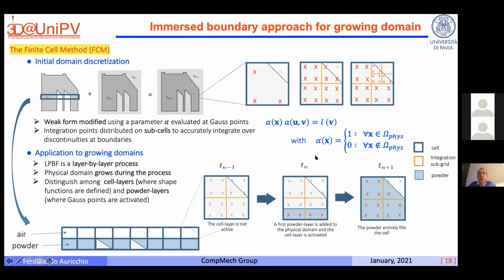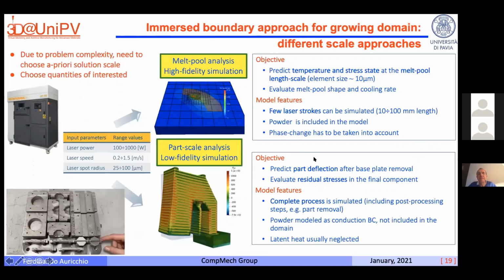But this approach is extremely flexible, and in fact, using this approach, we were able to perform a melt pool analysis, which we also name high fidelity simulations, and part scale analysis, which are clearly much lower fidelity simulations. And the idea, in any case, is either to describe locally what's happening or to get a very global response.